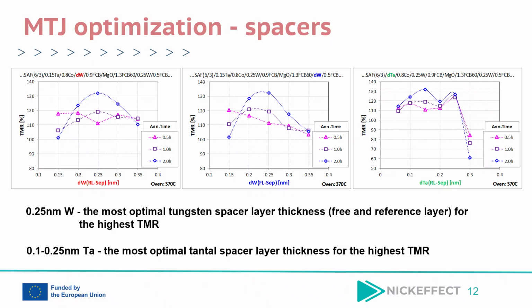The graph on the right presents the optimization of the tantalum spacer thickness in the RL spacer region. The best transport properties were obtained for tantalum thickness in the range of approximately 0.1–0.25 nanometer. For thicker tantalum layers, a strong degradation of TMR is observed, particularly after longer annealing times. These results demonstrate that precise spacer engineering plays a crucial role in achieving high TMR values and stable electrical properties of the MTJ stack.